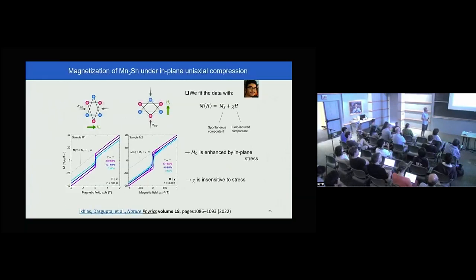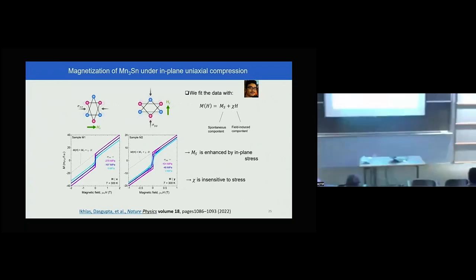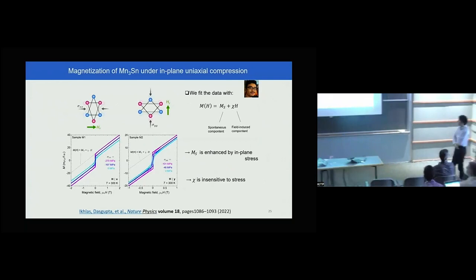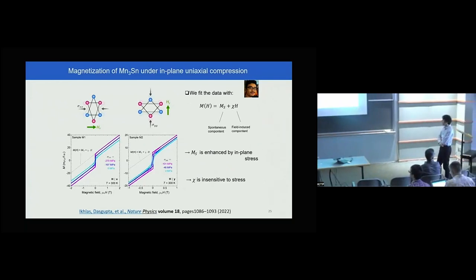Yeah. So the ultrasound attenuation has been measured, and yes, as you said, indeed there is a coupling between the phonon and magnetism, and the elastic modulus actually shows a strong anomaly at the Néel temperature.